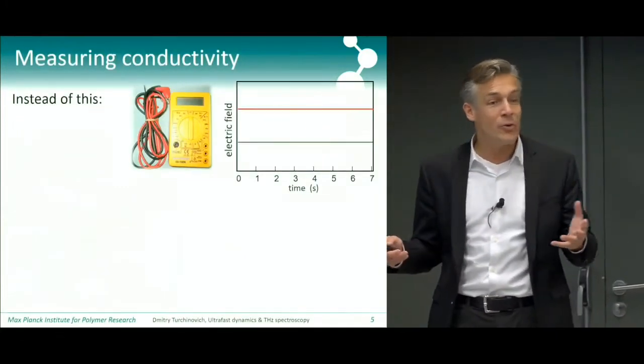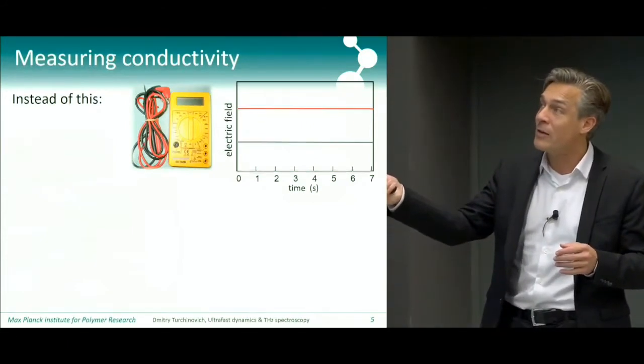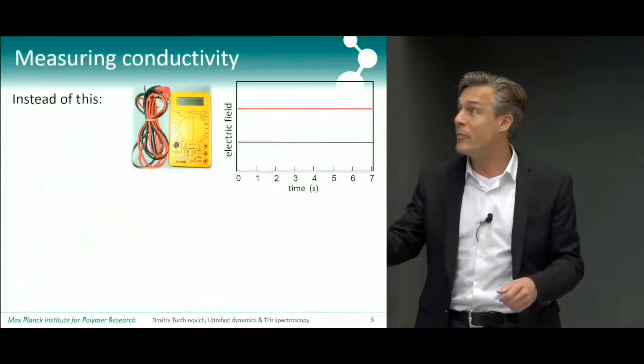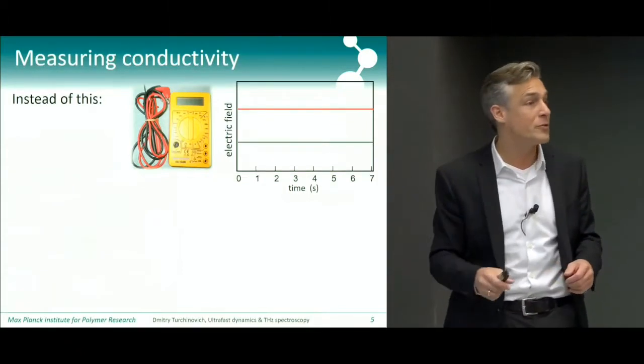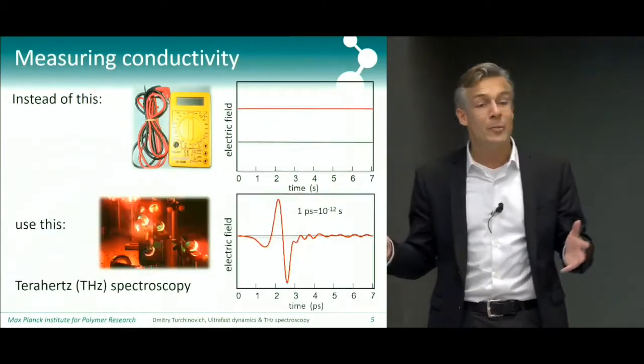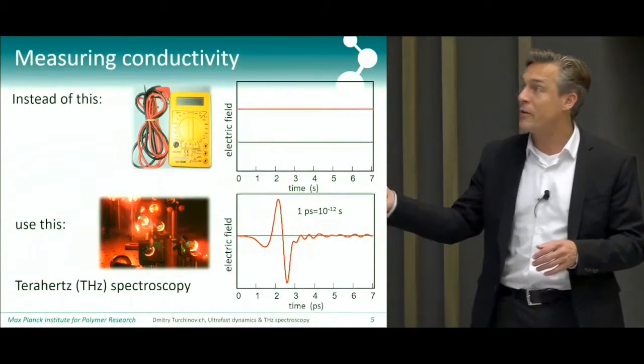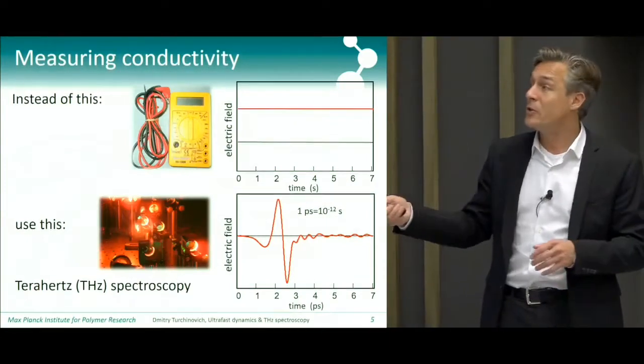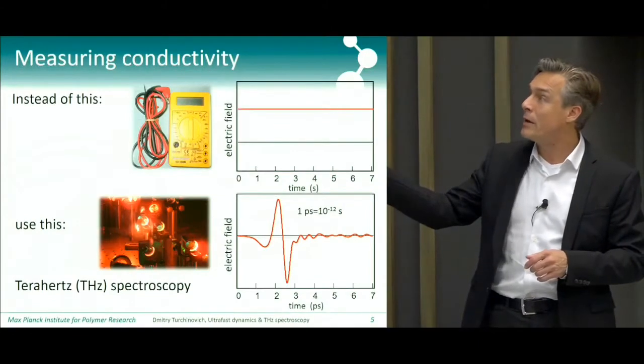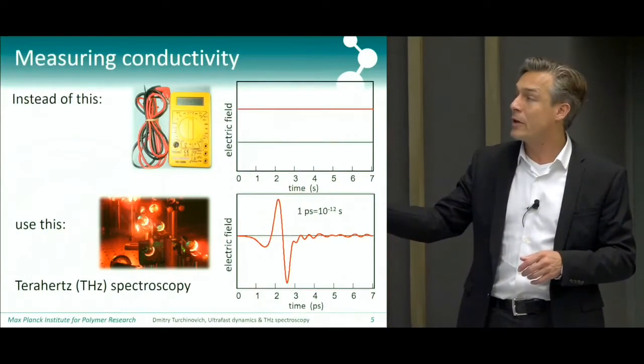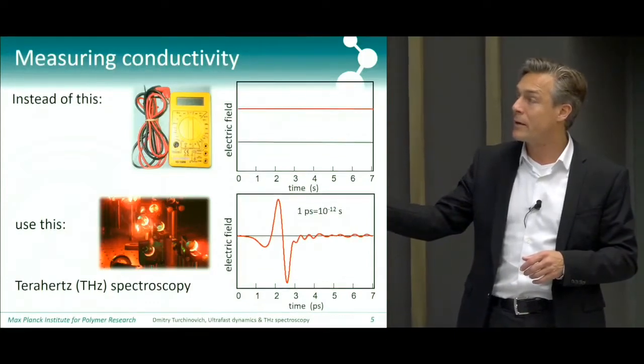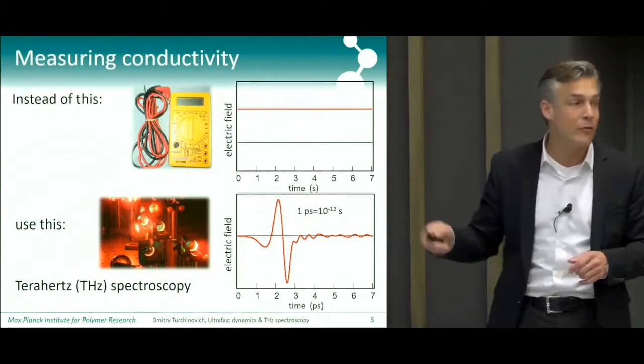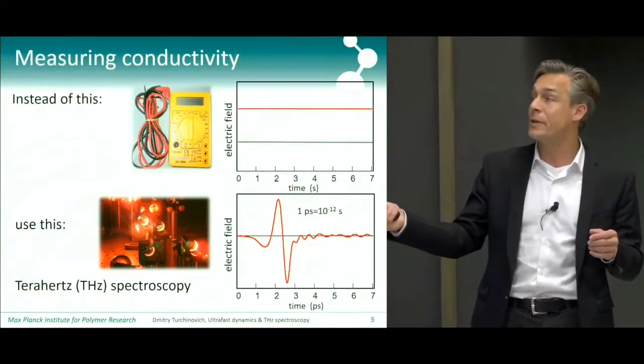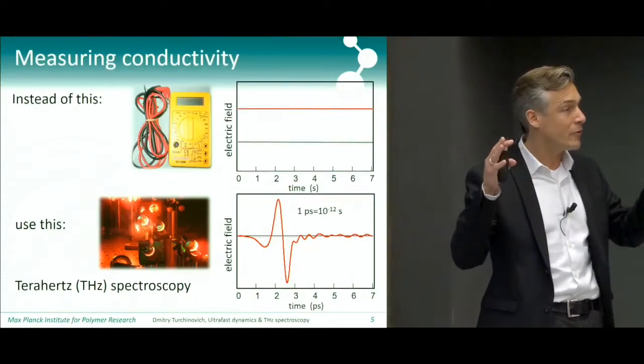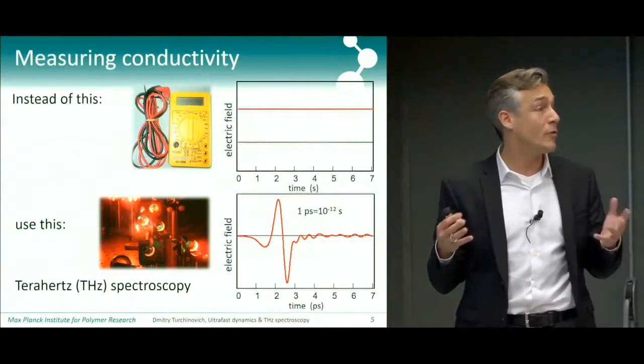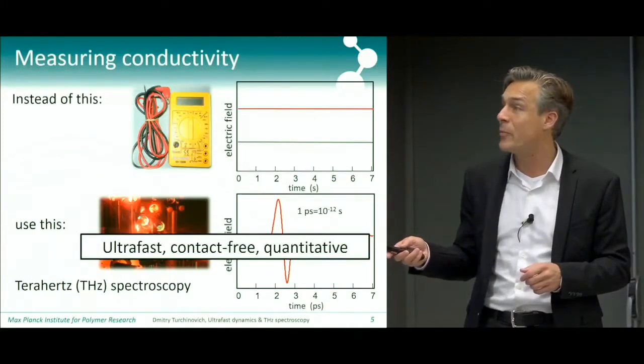You can, of course, put two contacts on graphene and apply a field and measure the current response of the material. This you can do, but I'm going to show you that there's another way of measuring the conductivity which is nice and useful, which is using terahertz spectroscopy. And rather than applying a field for a very long time, seconds, you can apply a very quickly oscillating AC field, and the oscillation time is about a picosecond. And the nice thing is that you can do this optically. So it just involves a lot of mirrors and laser beams. It doesn't actually involve contacts. And I'll show you that this is of great benefit.